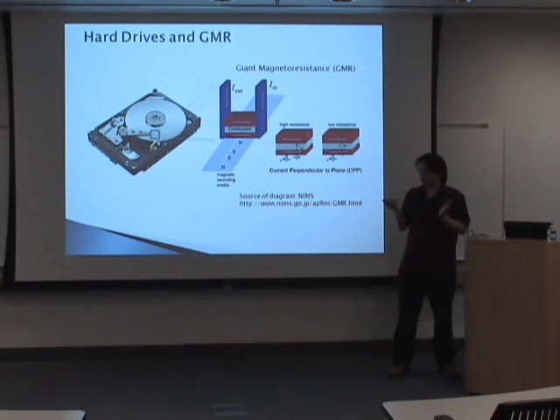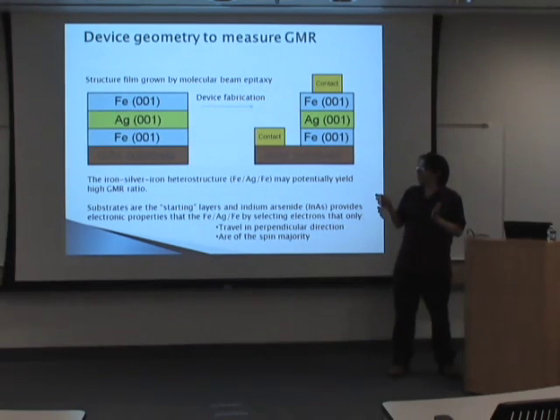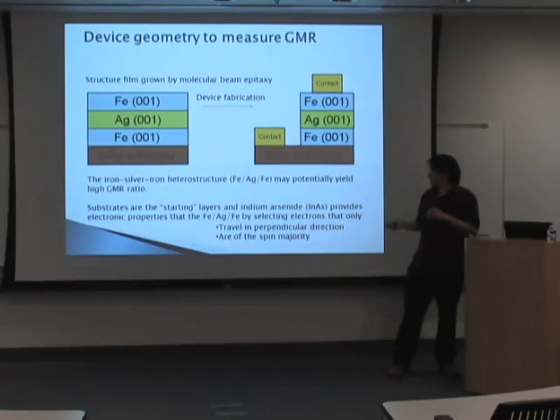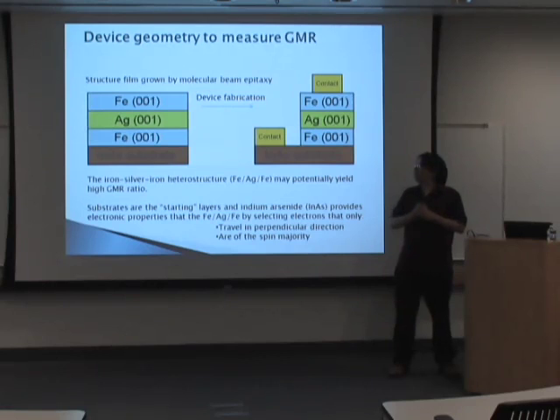And one of the proposed heterostructures is made of iron, silver, iron with an indium arsenide substrate, which is your foundation, the base. And you make this through a process called molecular beam epitaxy, in which you just get your substrate and shoot hot atoms at it. So you start with an indium arsenide wafer, and then you shoot iron at it, and then silver, and then iron, and then you grow this heterostructure. And the reason why I use indium arsenide in this case is because it does exactly what I just mentioned right there. It does what you want.